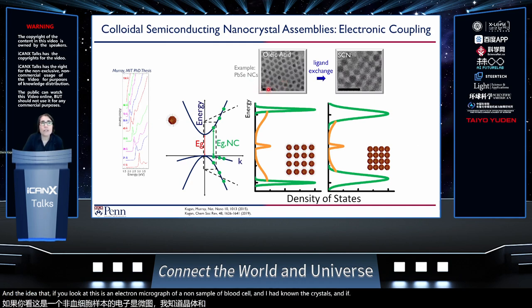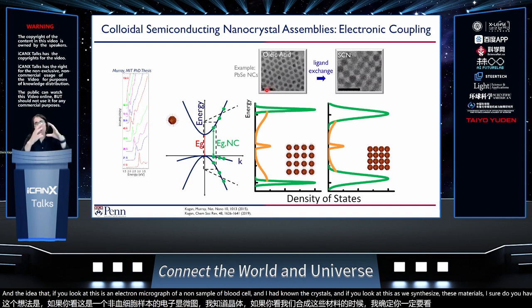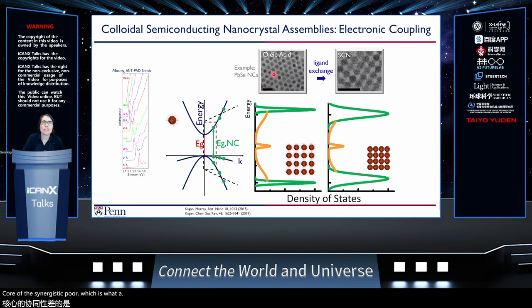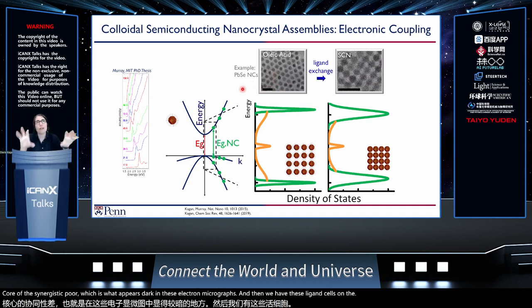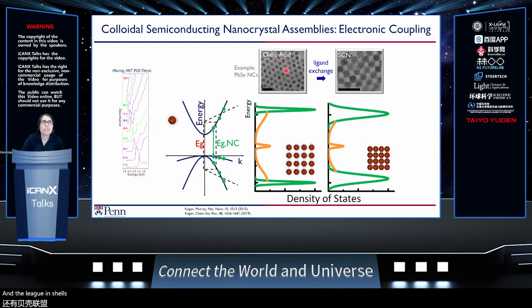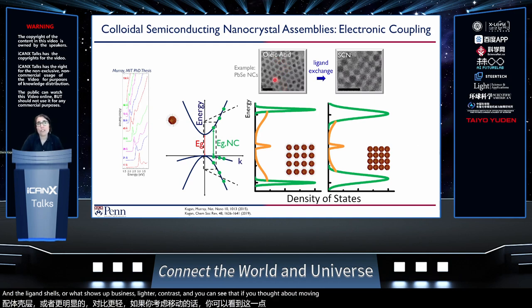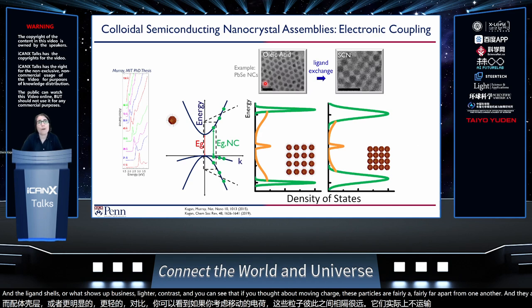As we synthesize these materials, I showed you we had this inorganic core, which is what appears dark in these electron micrographs. And then we have these ligand shells on the outside, and the ligand shells are what shows up as this lighter contrast. And you can see that if you thought about moving charge, these particles are fairly far apart from one another, and they actually don't transport charge very well.